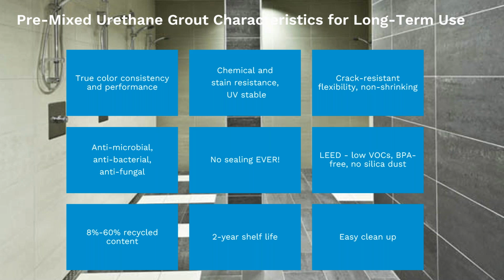With the urethane grouts, you do not have to seal it ever. It does contribute to your LEED credits, so it's low VOCs, BPA free, and no silica dust. That all gives you points towards LEED. It's 8% to 60% recycled content, depending on what type you get. It has that 2-year shelf life, so again, you can reseal it and use it at a later date if you do not use up all of the grout at one time, and it is easy to clean up.